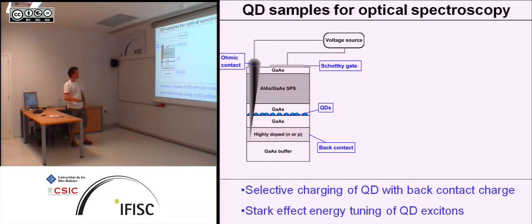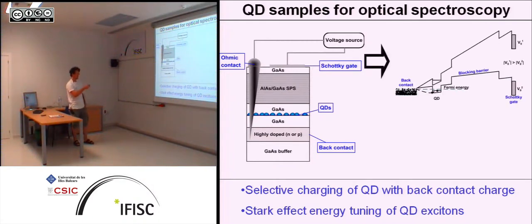On top of that, you do gallium arsenide, and then we have a semi-transparent metal top gate. What you can do now is put an indium material here, heat it up, and then this diffuses down into the highly doped region. That means you now have an electrical contact from the top to the bottom. And since this structure forbids electrons or any carriers from propagating from the top to the bottom, you have a capacitor here, so you can apply a voltage between the top of the structure and the bottom of the structure.